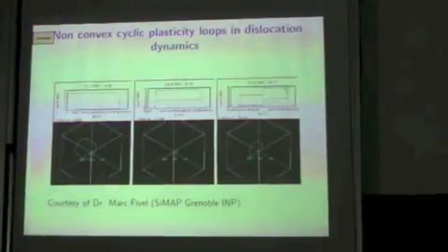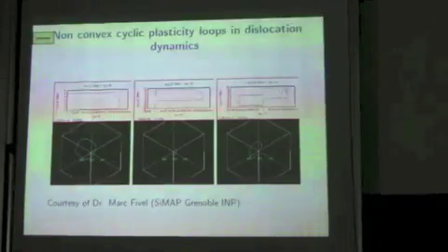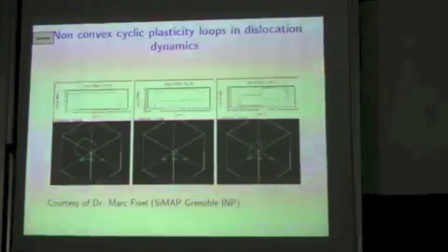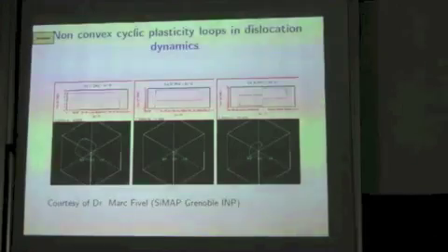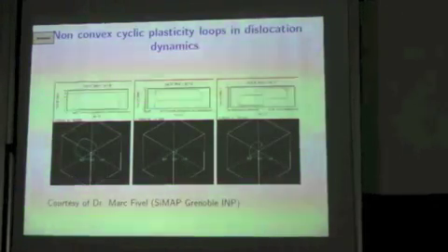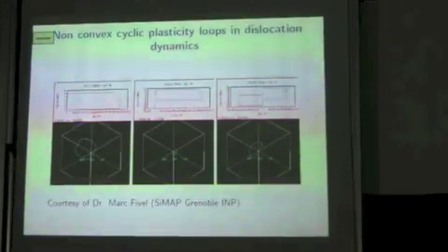In reality, of course, you have to add the cross slip and many mechanisms, and you don't see it in most cases, in fact. To operate, you must have, for instance, precipitates, where the size of the source is dictated by the distance between precipitates, and all the alloys I have shown here are reinforced with small precipitates. In fact, I thank you.